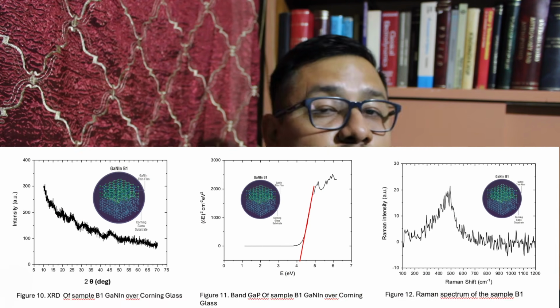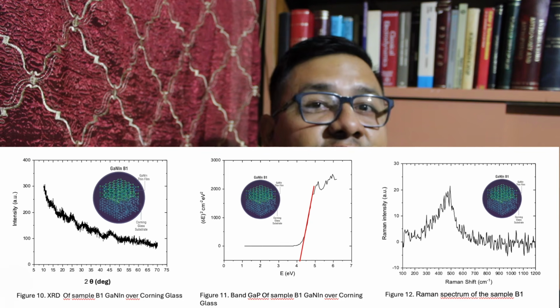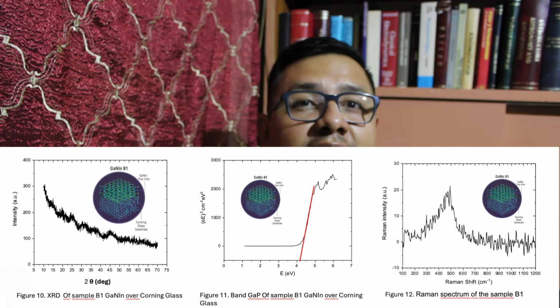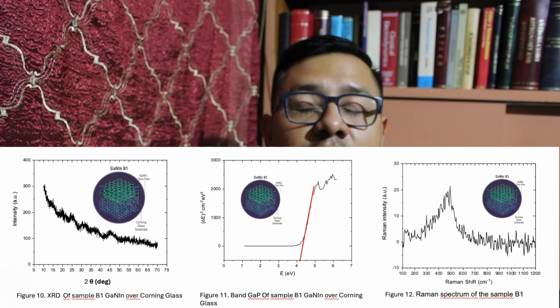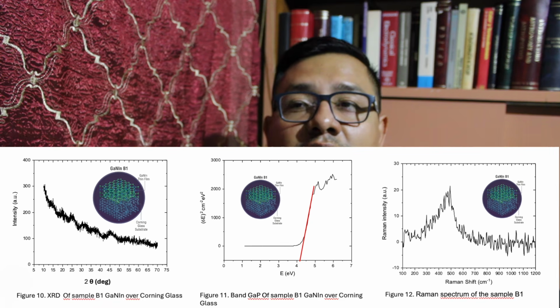In addition to this, the results of the thin films deposited with the gallium nitride and indium target have also demonstrated the efficiency and the impact of the presence of indium in the gallium nitride lattice.